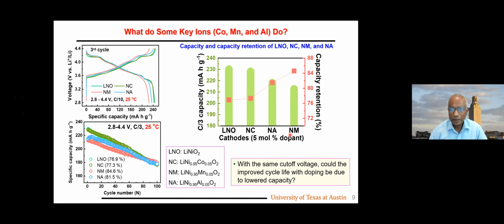So I give it in a different way. The bar graphs are capacity, the red dots are cyclability. Obviously, NM and NA cycle well, but the issue is, with the same cutoff voltage, could the improved cycle life with doping be due to the lower capacity? Because we are not comparing apples to apples: capacity is decreasing, the cyclability is going up.